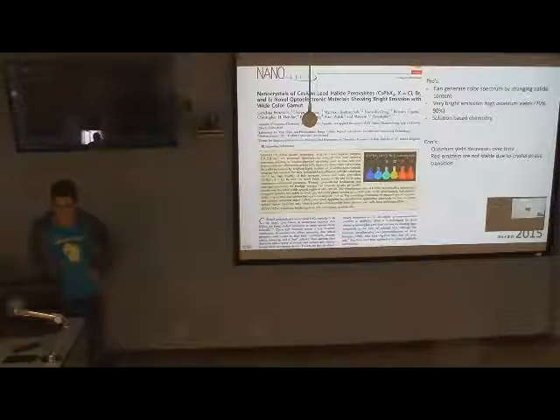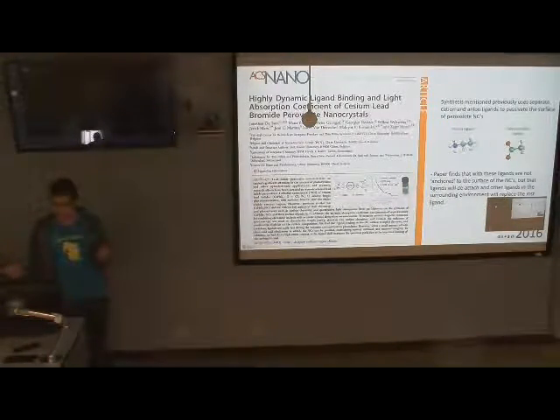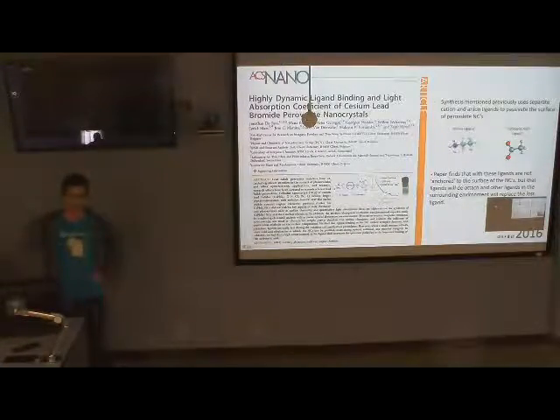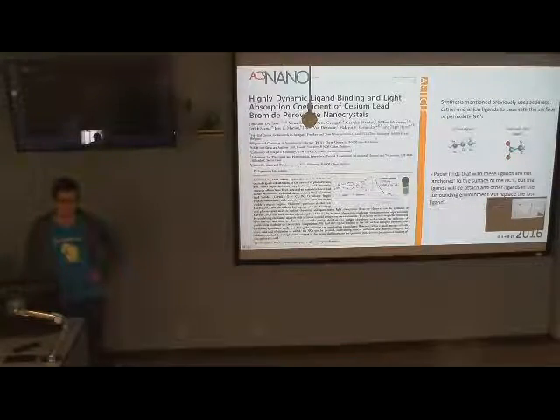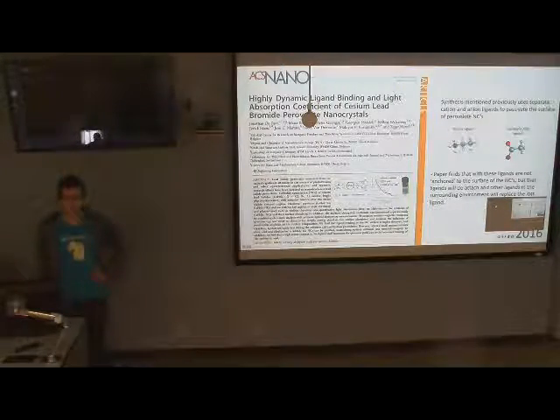When you go to the ligands, the story is you just need to passivate the surface. In this synthesis, they use ligands to solubilize everything, and then the ligands passivate the quantum dots to make them that small. This paper looked into the surface chemistry using NMR experiments I didn't really quite understand. But the summary is that the ligand environment is very dynamic. Ligands will pop off the surface of the nanocrystal, and in order for them to be stable, you need extra ligands within the solvation layer around it. As soon as one pops off, another goes back in, which isn't handy for practical applications, because in solid state you can't keep extra ligands around in the environment. So eventually the ligands keep popping off without being replaced, which creates surface states, which decreases the quantum yields over time.